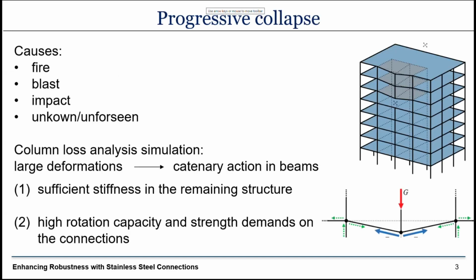So what we were trying to address was progressive collapse. Progressive collapse can be caused by a localized damage to a key structural component due to a number of reasons that can include fire, blast, impact loading, or any unforeseen or unknown hazard leading to a severe localized damage. As we can see in this figure, if a column loss happens, the beams converging to the segment of the column above the damaged column will be subjected to very high localized loads that will cause very high rotations to the connections and impose very high strength demands on the connections as well through large deformation of the remaining structure.